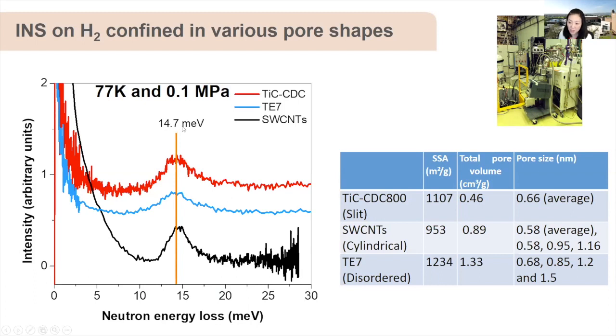And we see this solid-like hydrogen peak at 77 Kelvin and 1 bar for all three different shapes, which tells us pore size is the critical key factor in this process. This is actually good for material engineering, which improves the material engineering efficiency and reduces the cost of controlling or purifying pore shapes.